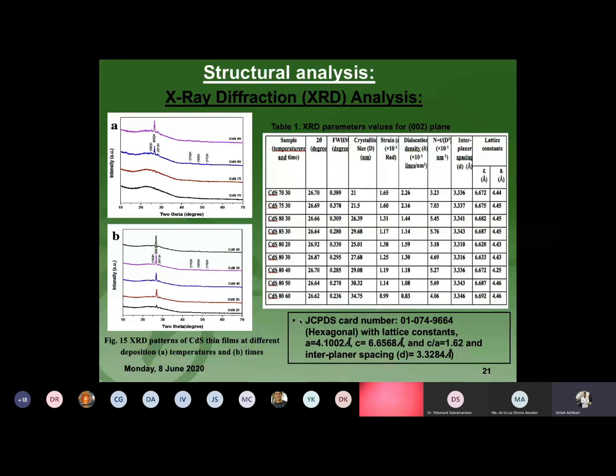We calculated the crystallite size from the 002 peak plane. From table 1, the crystallite size of the 002 peak increases with increasing temperature and time.